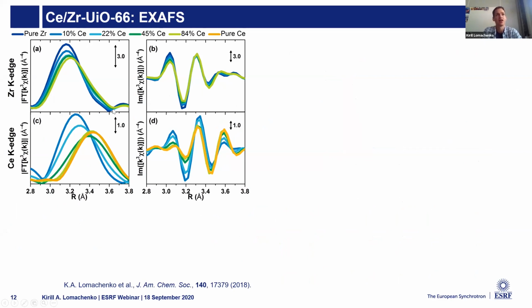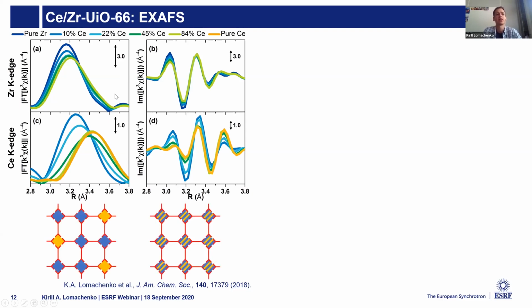Just looking at the spectra, zoomed on the metal-metal part, the peak responsible for metal-metal interaction, it's very clear that we don't have a segregation of the cornerstones. Because if we had only the pure cornerstones, the spectra shouldn't have varied at different cerium content, since for each particular cerium or zirconium atom the local environment wouldn't change at all as a function of cerium content.